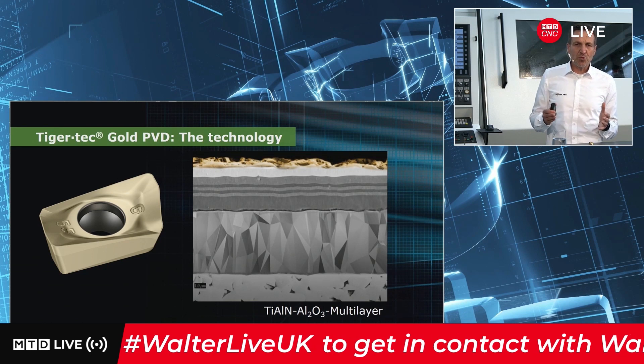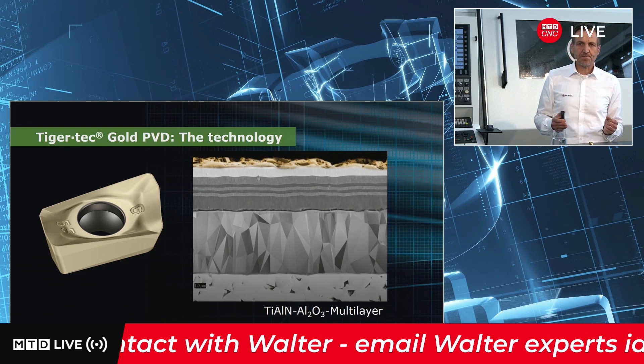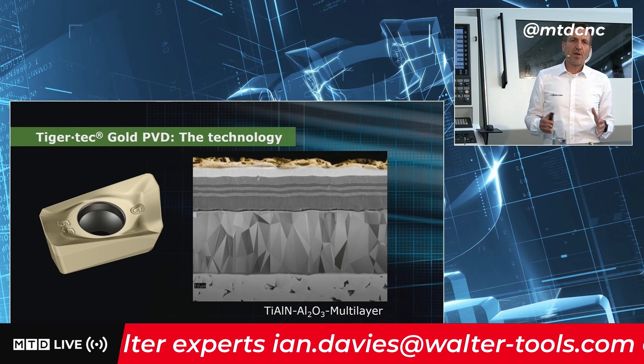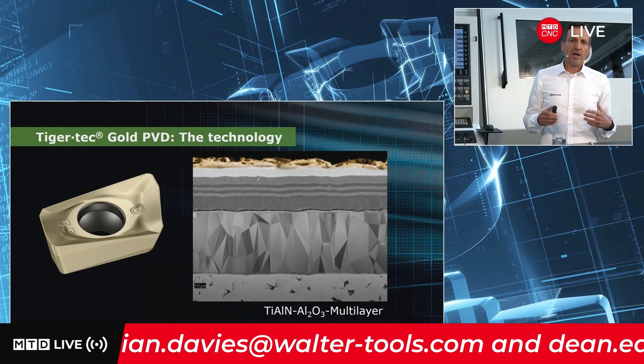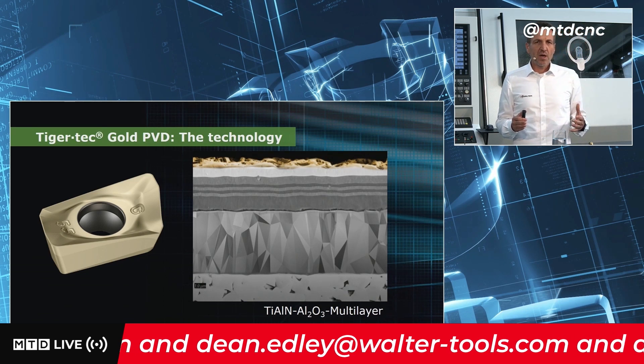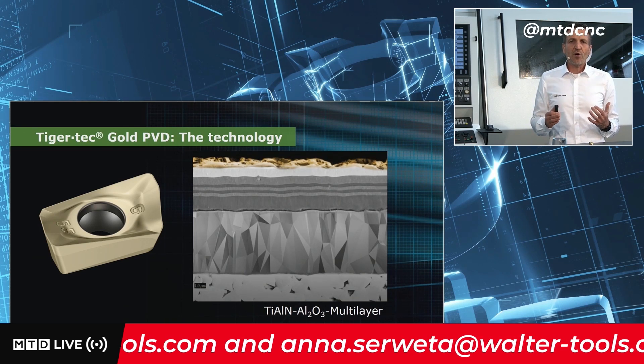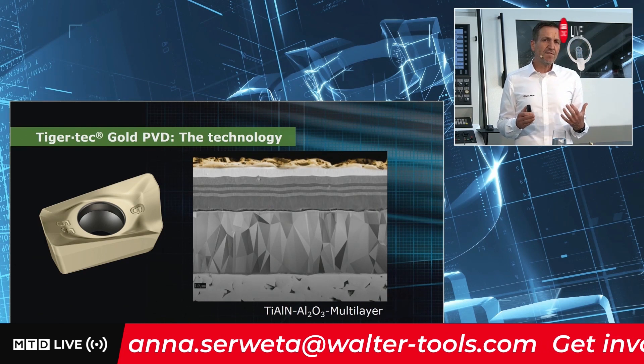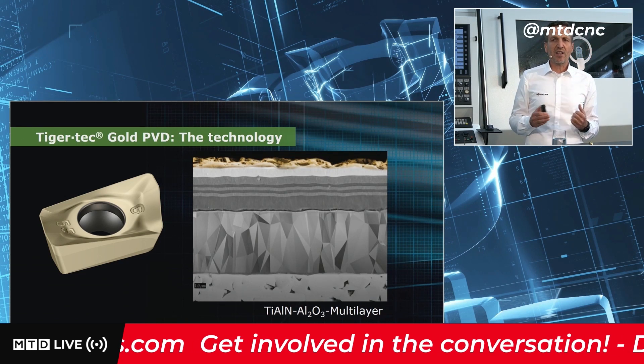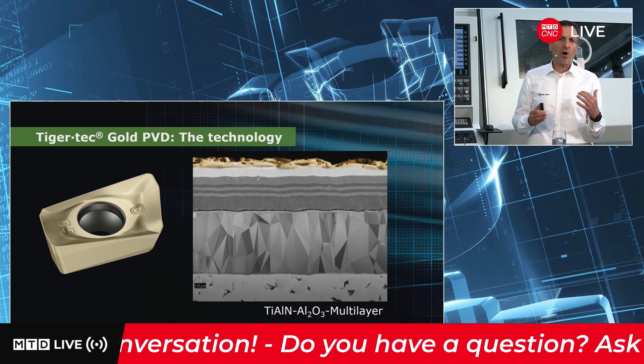The high hardness of the titanium aluminium nitride reduces the flank wear, which also increases the tool life. In combination with that, we have a special mechanical post treatment to avoid thermal cracks and to avoid chipping off the cutting edge. Thermal cracks are a typical wear pattern in milling — we have different temperature levels when the tool goes in and out of cut. Therefore we designed the insert with a light gold colored top layer, so you can always see if the cutting edge is new or already was in use.